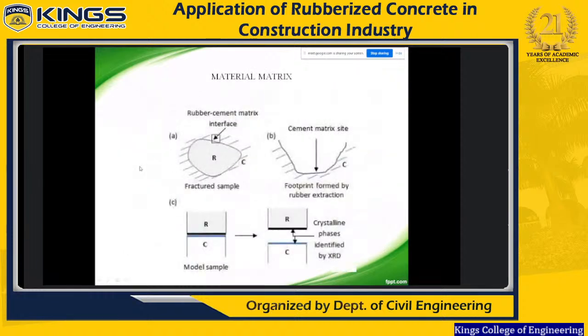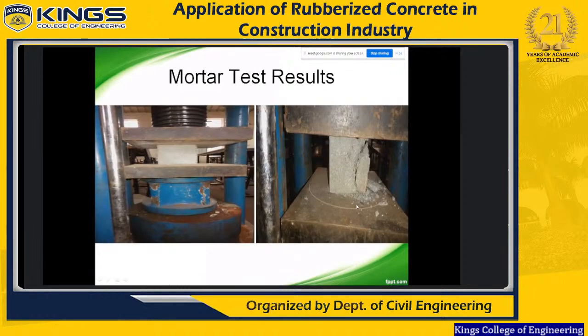So how is the bond between the rubber and cement matrix interface? With rubber and cement, the bond will be seen in the fracture sample, somewhat in the cement matrix, with the footprint from rubber extraction. In the rubber and cement model, a somewhat crystalline phase is also identified here in the XRD pattern. So we are conducting the mortar test in our laboratory.